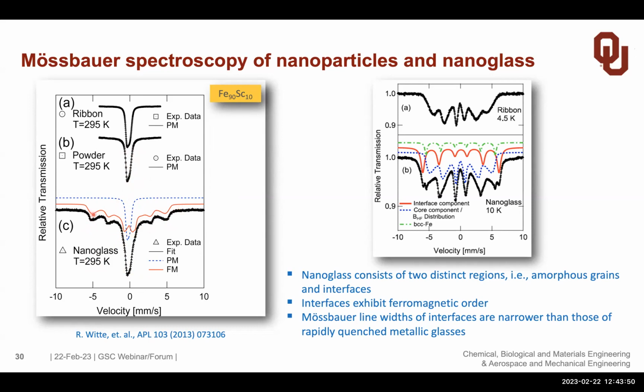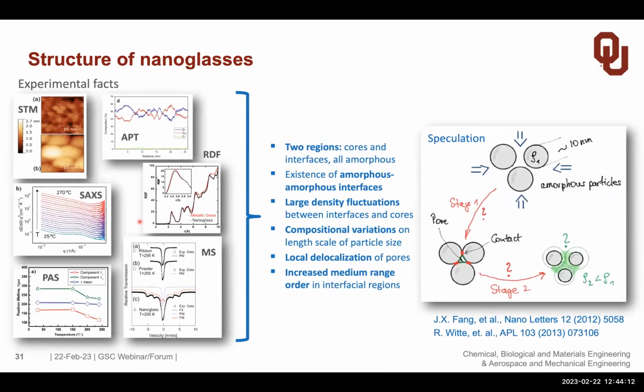Second of all, it's a phase which was not there before. If you change the particle size, get smaller or bigger, you change the fraction of that red component, which indicates that this is the interfacial region between these amorphous particles. So indeed, we have formed a new metallic glass structure. There is a lot of other experiments which we have done, and it would go beyond this talk. But what we can say is that we have large density fluctuations between the interfaces and the cores of this. It's all amorphous, but it's clearly a different amorphous structure.